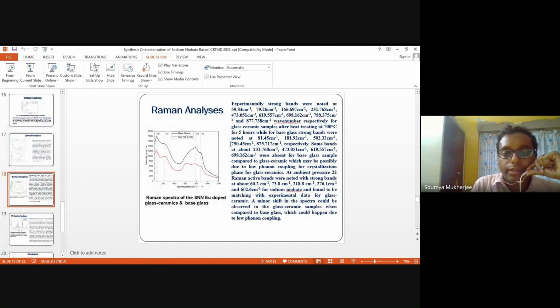Next is the Raman spectral analysis, which has been carried out, and we have compared with the base glass, and there are some changes which we observed. So these are the strong bands that we have observed. Some bands are not observed in the base glass, while some are observed in the glass ceramic systems. This is due to the phonon coupling of the crystallization process, with low phonon coupling. So minor shifts in the spectra are noted if we compare the glass ceramics with the base glass.